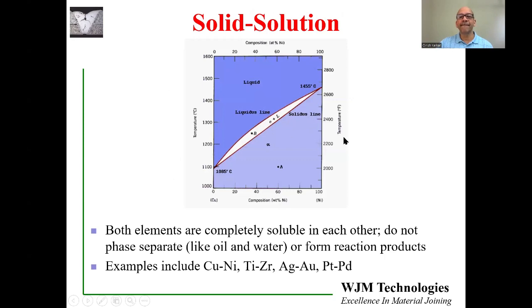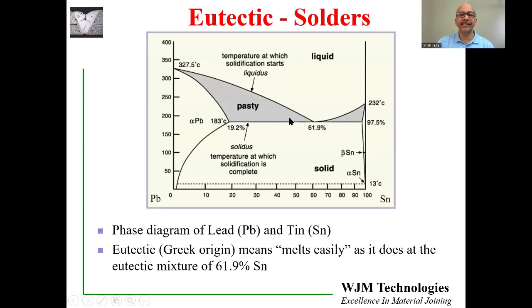So here again, there is a melting range, similar to what we had in copper-nickel. Now, how do we take benefit of that melting range? In that melting range, where you are in the middle over here, where it's partially solid, partially liquid, the solder alloy is quite viscous. And we can use that behavior to bridge larger gaps between components. So you can tailor the molten behavior, not completely molten, but partially molten, to your benefit in process control if you're trying to bridge smaller or bigger gaps. If you're trying to bridge very thin gaps, then a eutectic mixture is good. But if the gaps between components are bigger, then a non-eutectic mixture would be beneficial to bridge those gaps.